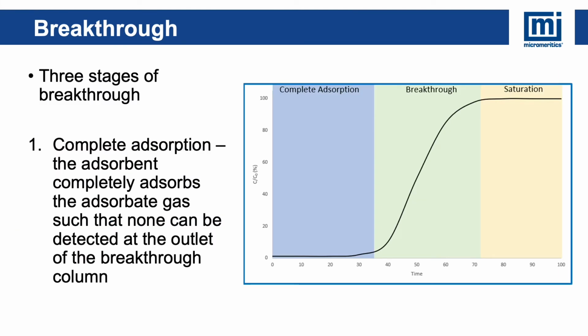After we collect breakthrough data, it's commonly referred to as a breakthrough curve. Essentially what we do is we plot the concentration and how that changes versus time. Shown here is an example breakthrough curve broken down into three sections: complete adsorption, breakthrough, and saturation. During complete adsorption, the adsorbent completely adsorbs the adsorbate gas such that none can be detected at the outlet of the breakthrough column. This is shown in the blue section here, where we cannot detect any of our adsorbate gas in our mass spectrometer because it is being completely adsorbed by our breakthrough column.